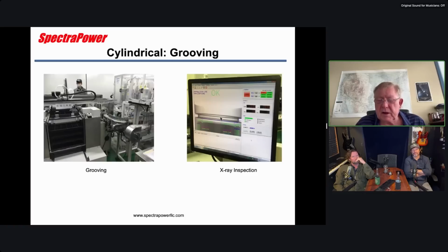And this is kind of interesting. You can see the X-ray inspection of the groove. And that's important because you have to do a lot of preventive maintenance in lithium-ion plants because the equipment is wearing. So in this case, the grooving tool can wear, which will cause you to not have enough of a groove or to have too much. In which case, if you have a safety incident, it'll just blow the cap off of the cell.